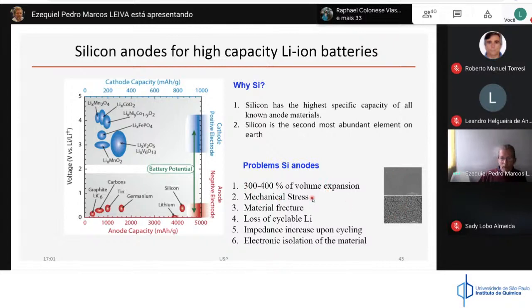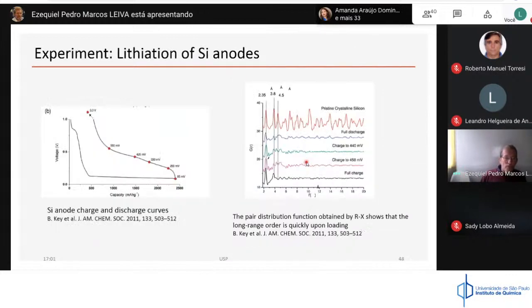You get mechanical stress, you get material fracture, you lose a lot of lithium because these cracks break down the material, and you lose contact of the silicon in the anode. So there are a number of problems with silicon that need to be addressed. And for this reason, we decided to simulate by molecular dynamics the insertion of lithium in silicon anodes.